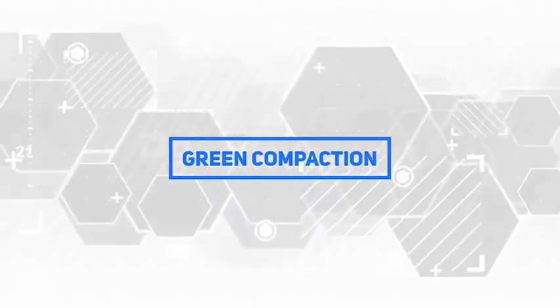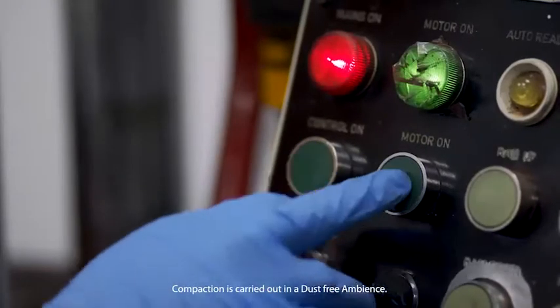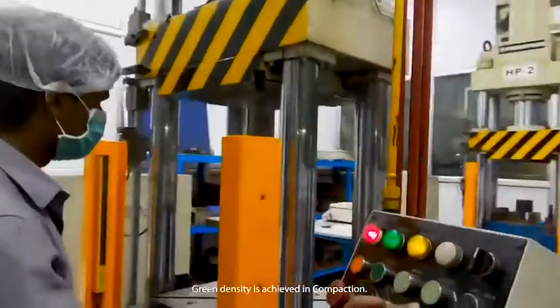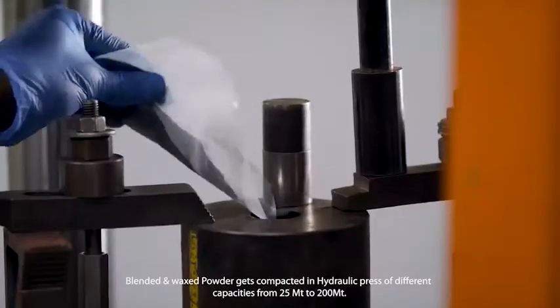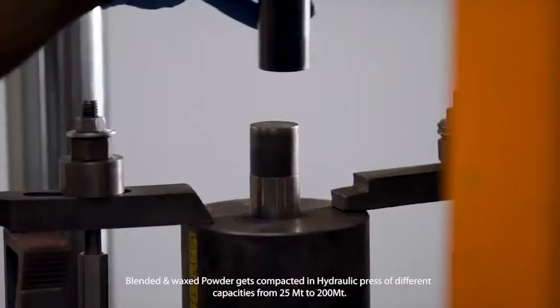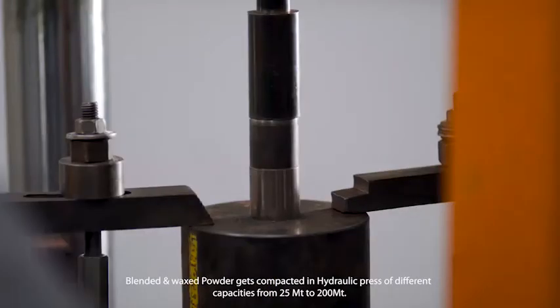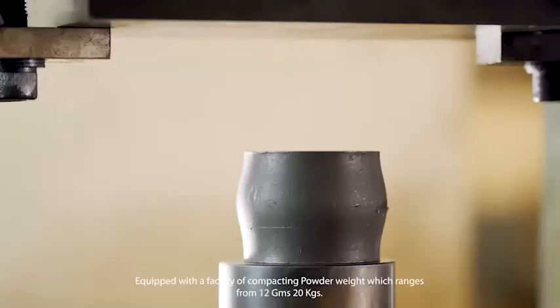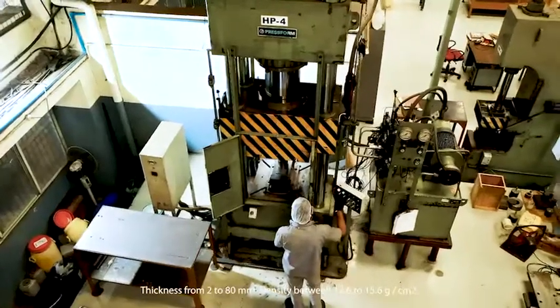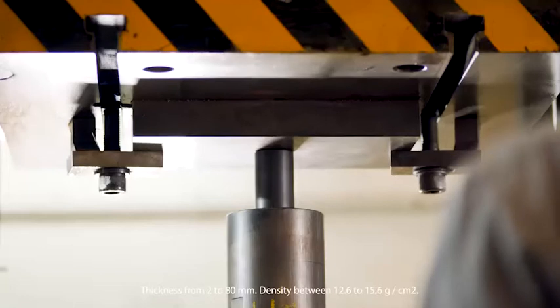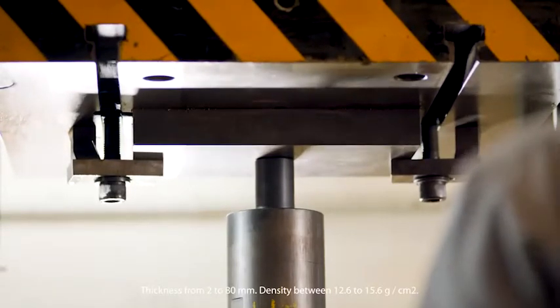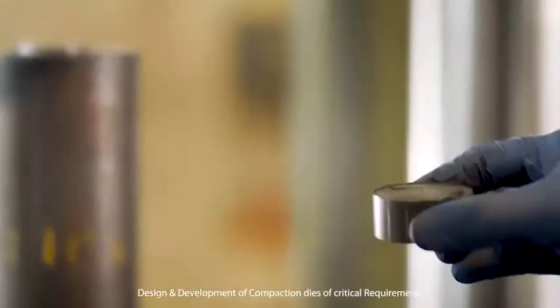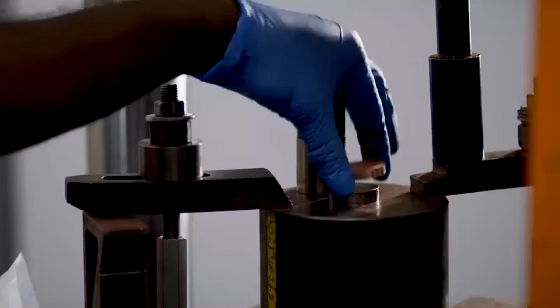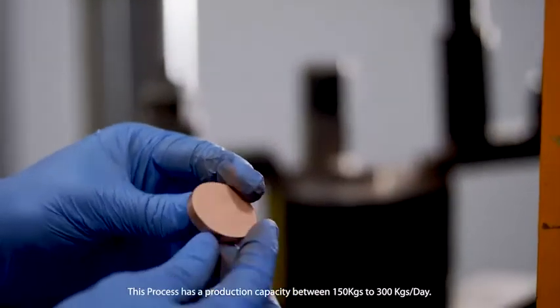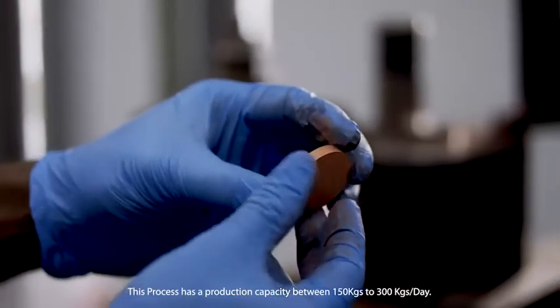Green compaction. Compaction is carried out in a dust-free ambience. Green density is achieved in compaction. Blended and waxed powder gets compacted in a hydraulic press of different capacities from 25 metric tons to 200 metric tons. Equipped with a facility of compacting powder weight which ranges from 12 grams to 20 kilograms, thickness from 2 to 80 mm, density between 12.6 to 15.6 grams per cubic centimeter. Design and development of compaction dies are of critical requirement. This process has a production capacity between 150 kg to 300 kg per day.